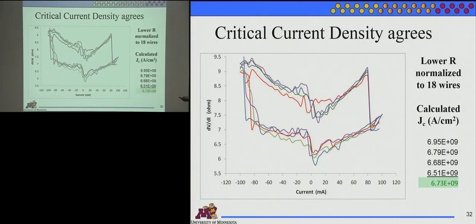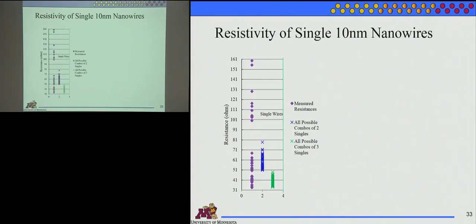No changes. Taking a little noise around 0. But that current switched at exactly the same spot. These currents switch at different currents because there actually were more wires there. We just adjusted the height so we could see what the loop looked like. So for sure, if you pick up the same number of nanowires every time, you're going to get the same switching current density. And we think it's a very high switching current density, which again we want for a read head. And we were pretty happy with that result.